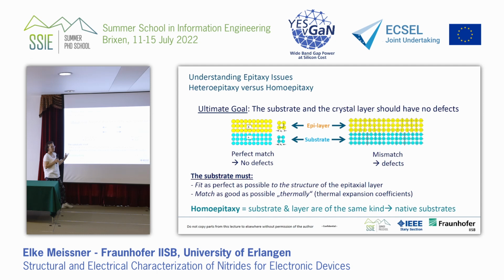And of course we have to adapt the lattices, because if you put atoms now on all of these atom balls, you put other atom balls, then they don't fit at the same places, so they are being displaced. And displacement in an atomic lattice means you form and create a dislocation. So the substrate must fit as perfect as possible. This would be the ideal case. Then you have no dislocations and you don't have problem with heating and cooling. And it has to match as good as possible in thermal respect.